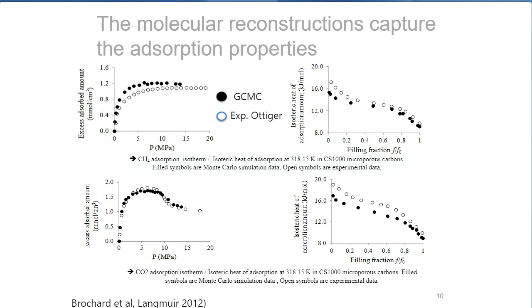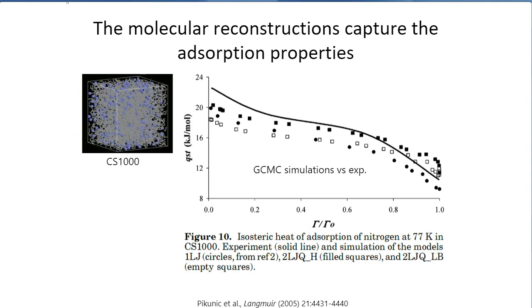We did the same calculation for nitrogen in porous carbon CS-1000, and for once we did the simulation before the experiment — a real prediction. We compared with the experiment run by Philippe Llewellyn, our colleague now with Total Energies in France. Not only was the comparison interesting as a prediction, but we also understand this decreasing function. That single curve tells you that in no way does a porous carbon behave like graphite or graphene for adsorption.